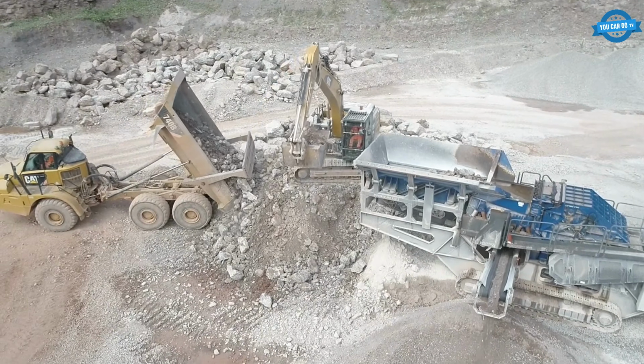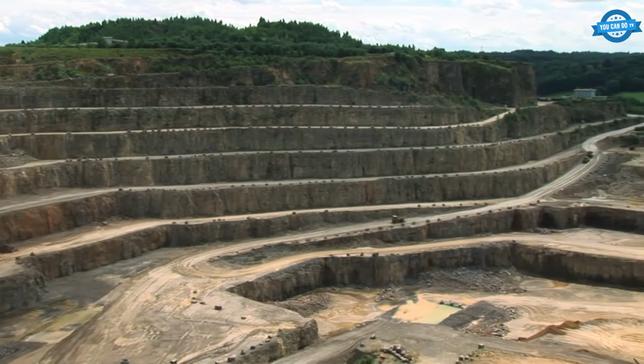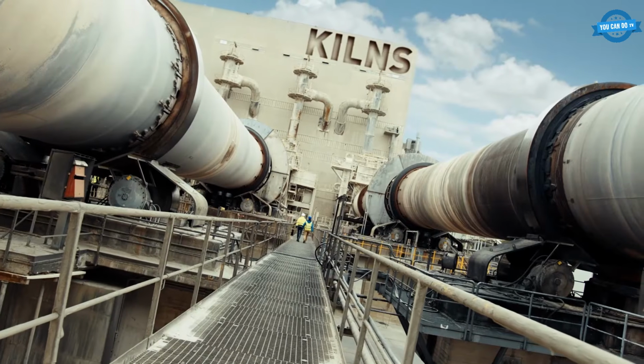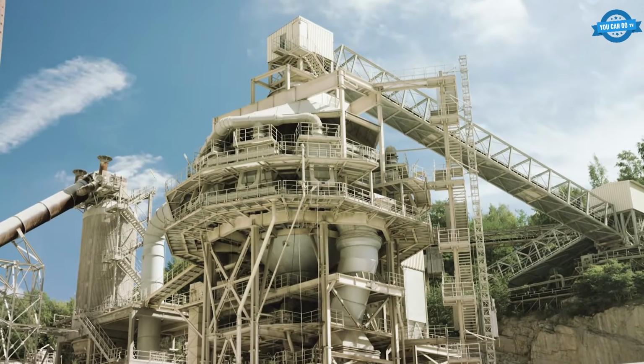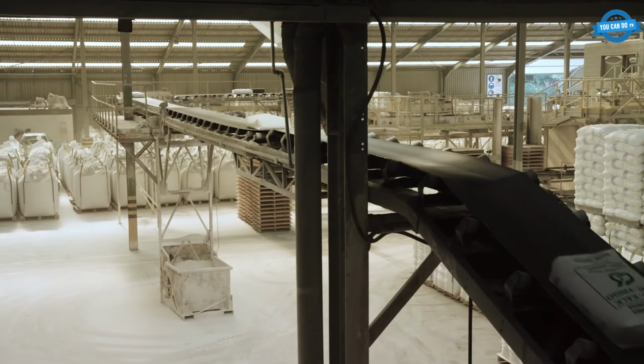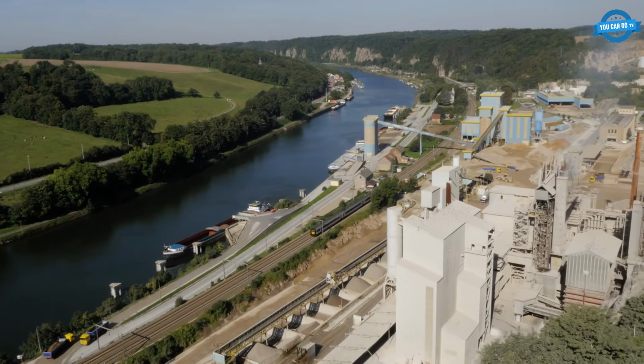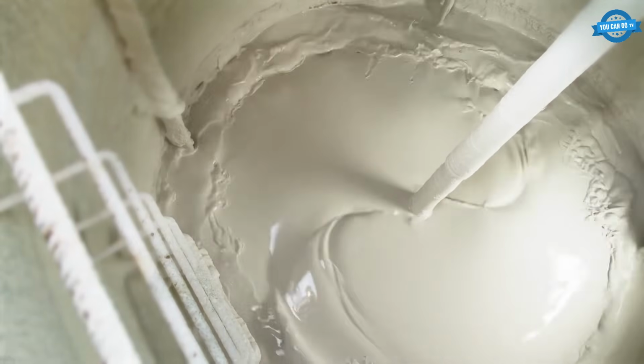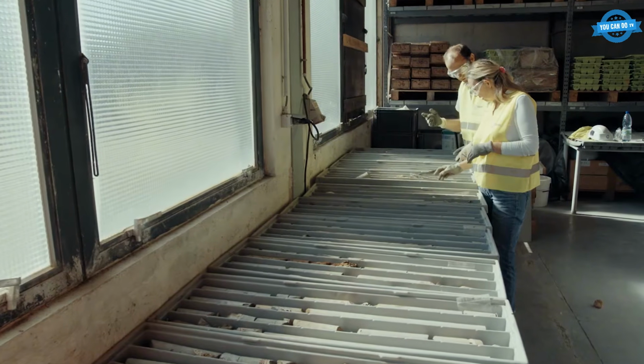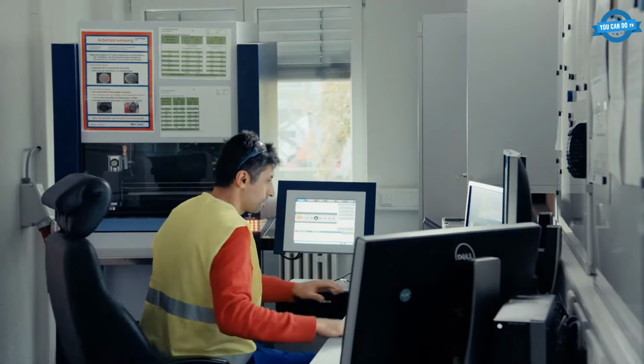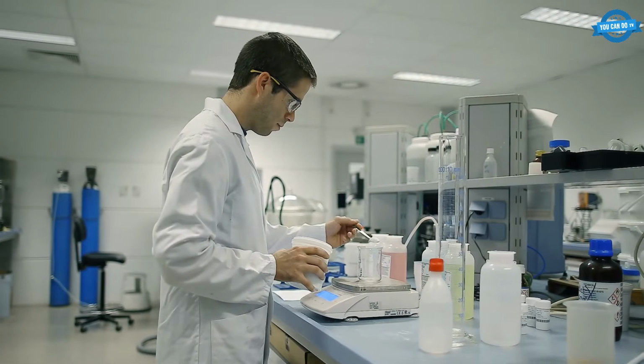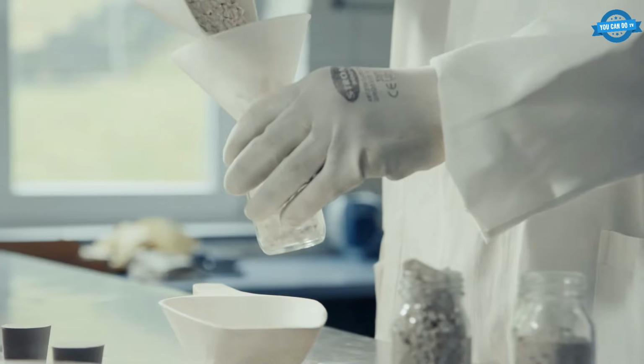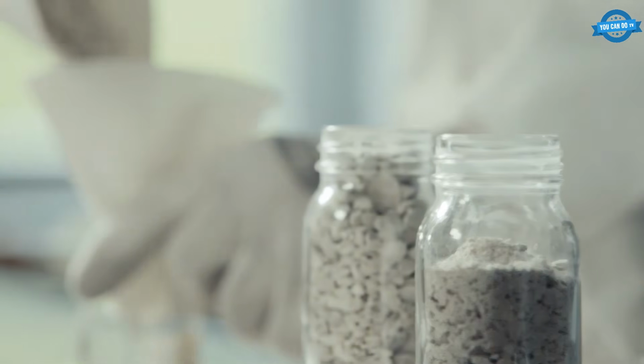Step back to a full lime operation and you see something closer to a chemical refinery than a mine. Multiple kiln types run in parallel. Long rotary kilns with preheaters, annular kilns, parallel flow, regenerative shaft kilns. Each tuned for a different product grade. Downstream, milled lime, hydrated lime, and milk of lime peel off as 3 separate product streams. Every batch is sampled, tested, and tracked. Rail, road, river, and deep water shipping all leave the same plant because lime is heavy, and moving it far by truck alone would kill the margin.